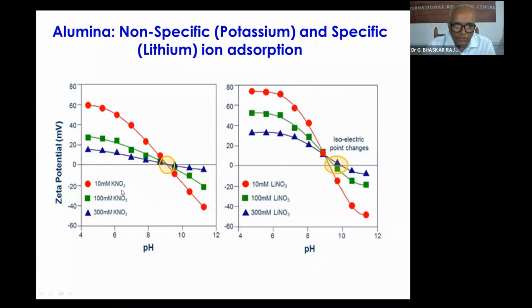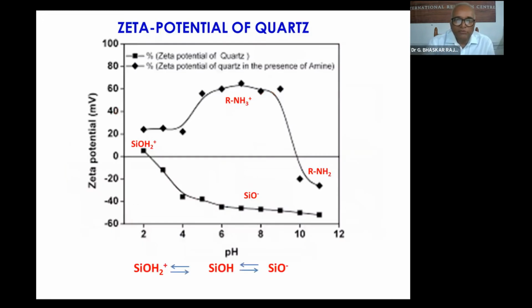Commonly, potassium nitrate is being used, and sodium sulfate also is used in some instances. Sodium chloride we can also use for conductivity. But at the same time, it should not get adsorbed on the interface. So we have to use indifferent electrolytes. Once we ascertain that they are not interfering, the same electrolytes we can use for our zeta potential measurements.